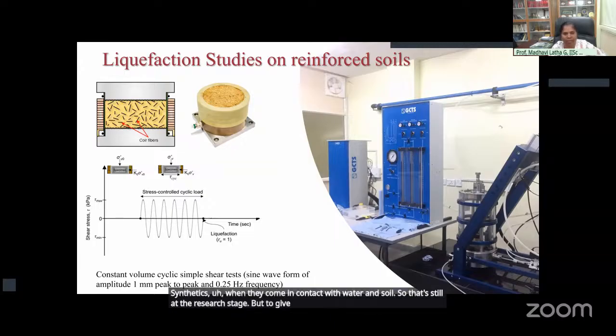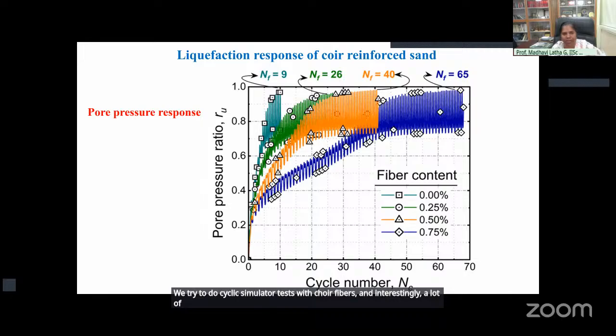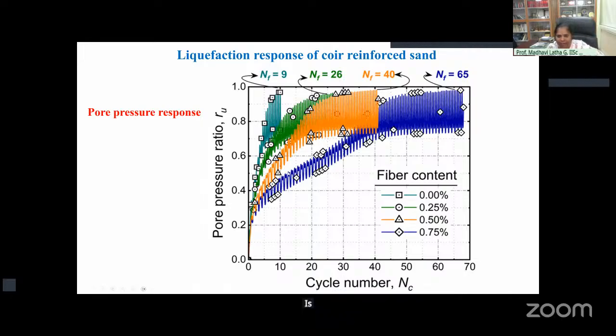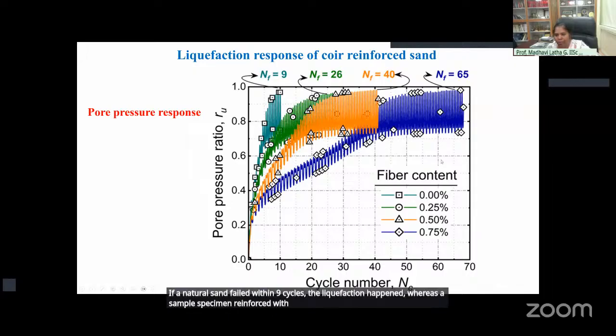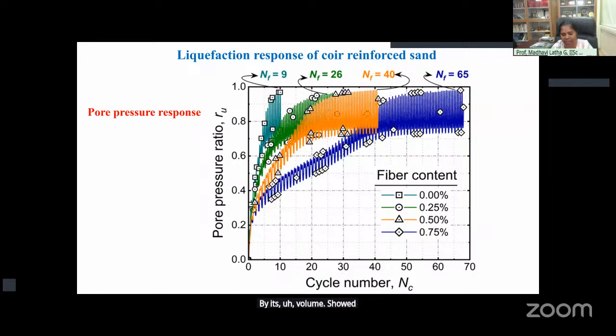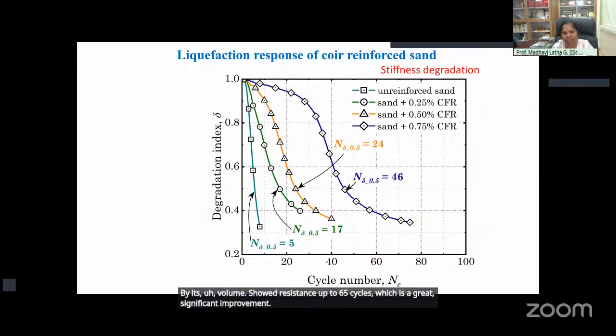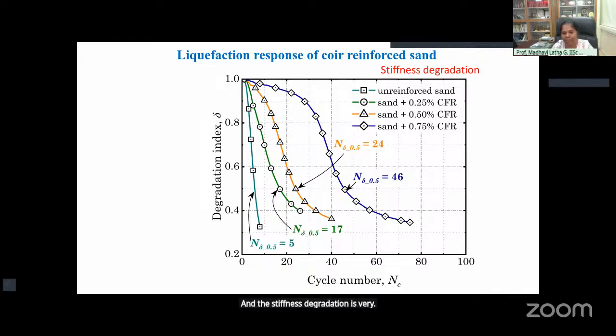But to give you a brief on how these materials can be extremely beneficial under conditions prone to liquefaction, we try to do cyclic simple shear tests with coir fibers. And interestingly, a lot of earthquake liquefaction resistance is exhibited by the samples which are reinforced by coir fibers. If a natural sand failed within 9 cycles, the liquefaction happened, whereas a specimen reinforced with coir fibers to 0.75% by its volume showed resistance up to 65 cycles, which is a great significant improvement. And the stiffness degradation is very, very slow in case of reinforced specimens.